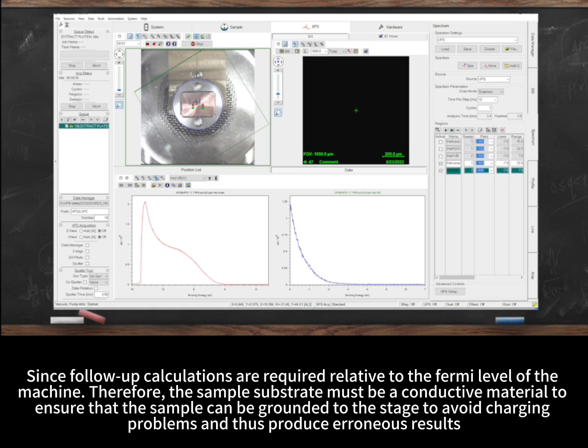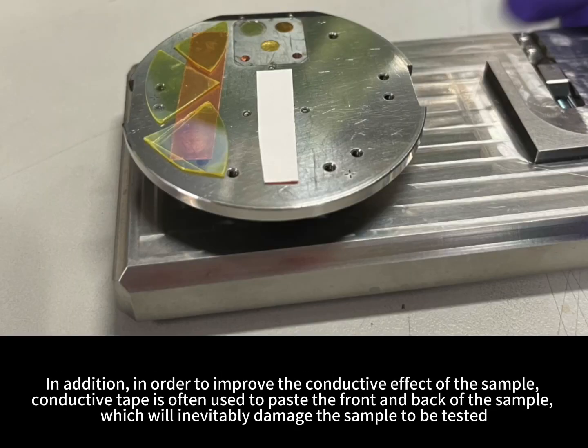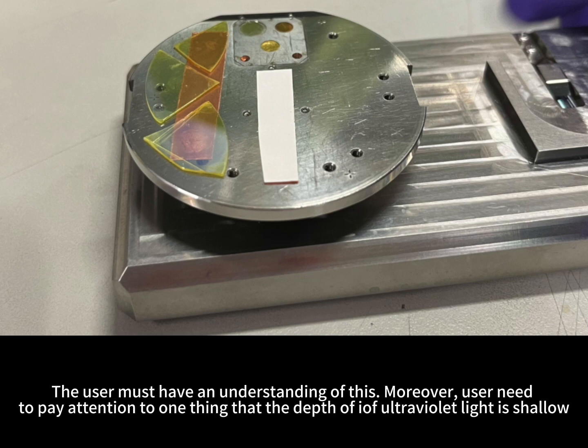erroneous results. In addition, in order to improve the conductive effect of the sample, conductive tape is often used to paste the front and back of the sample, which will inevitably damage the sample to be tested. The user must have an understanding of this.